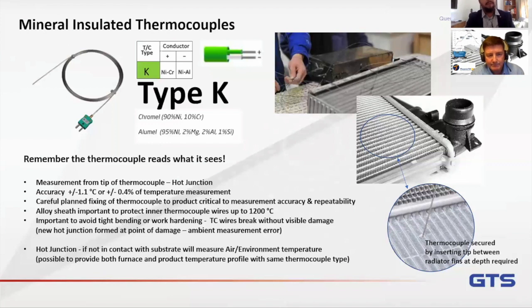We do not recommend the fiberglass insulation because we normally use type K thermocouples, which are made of nickel and chromium. The problem with chromium is that it's very reactive. So every time you reuse the thermocouple, you're losing material, or the chromium is reacting with other metals. So we prefer that you use mineral insulated thermocouples, which on this side of the sea we call MgOs, from magnesium oxide.